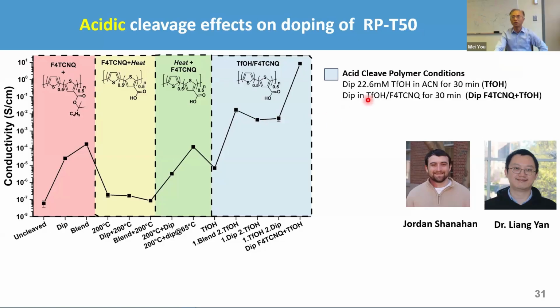But once you dip your polymer into the triflic acid and F4TCNQ mixed solution, you all of a sudden can make conductivity as high as 10. So if you go from 10 to the -6 before doping to the 10 after this particular doping, you end up with a conductivity difference of 10 to the 6 or 10 to the 7. And that's the power of using the mixed acid plus F4TCNQ.